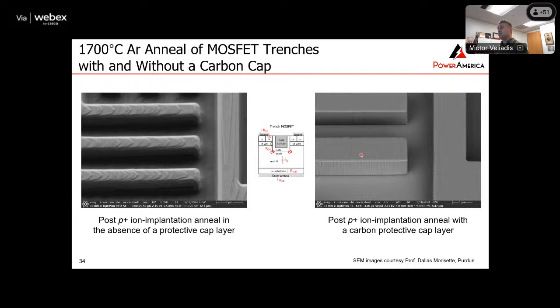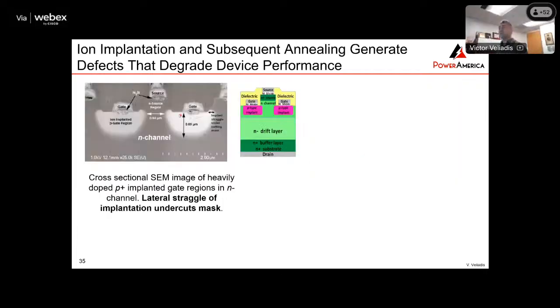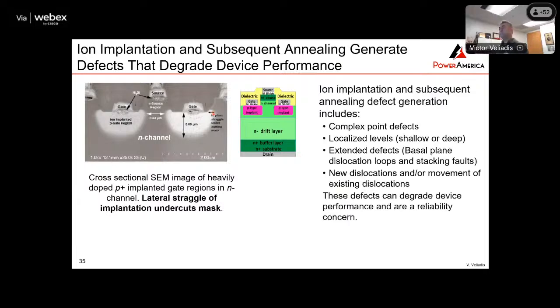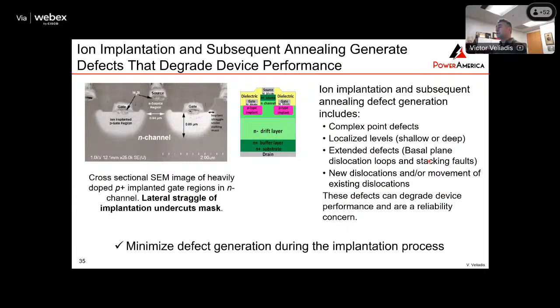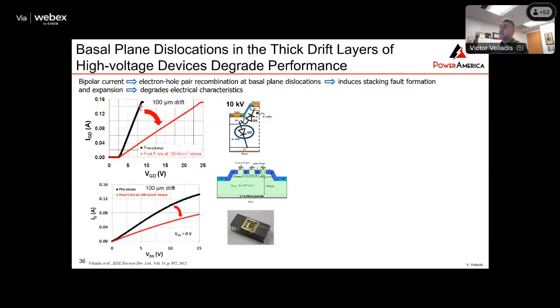Okay, now this is an example of P plus implantation. This region, you see there's a small implant straggle that you need to take care of. And the issue is that when you do the implantation, unfortunately, you can introduce defects. So there are defects that are introduced during the implantation process. And I mentioned some of these defects here. One of the worst ones is the basal plane dislocations, because those are detrimental to the device. So when you do the implantation, you need to develop the process in a way that you minimize the defect.